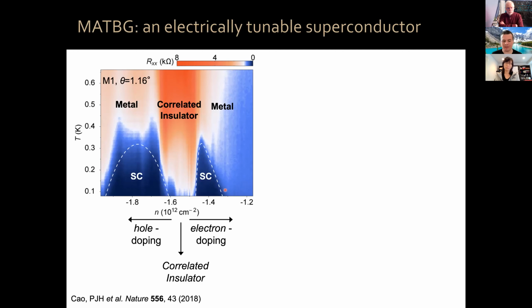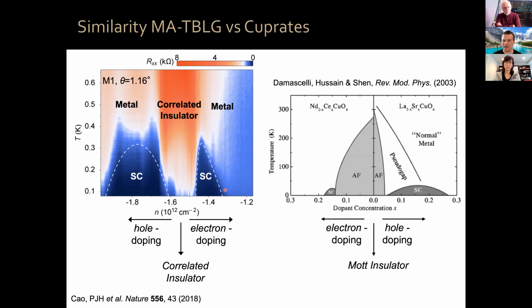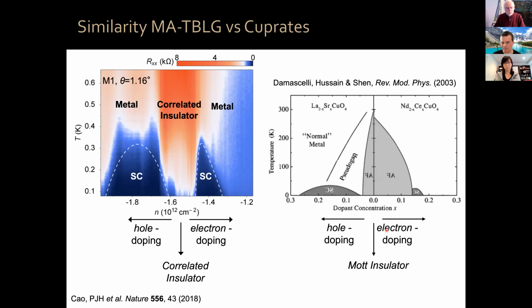Okay. Now, when my students showed me this, it immediately reminded me of the hundreds of times I've seen this type of phase diagram. Okay, these are the phase diagrams of the cuprate family of high temperature superconductors. In a temperature versus doping diagram, let me flip this axis for electron-hole doping so that they look the same as here. Okay. Now, at 0 doping, which means 1 electron per unit cell for the cuprates, it's a Mott insulator. You add extra holes, you have a big superconducting dome. You add electrons, you have a smaller superconducting dome.